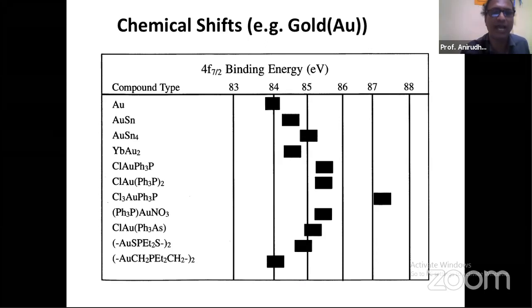This is a slide which shows different binding energies and binding energy shifts for an element like gold. The website Lasurface, which I mentioned a little while ago, would give information similar to what I have shown here, though not in the form of this graph. It would simply give those values. For example, gold shows a binding energy of 84 for 4f7/2. We will see what that 4f7/2 is. When gold is bonded with stannum, tin, Sn, the 4f electron binding energy for gold shows a shift, almost 84.5. When it is AuSn4, its value shifts to 85, and then you get a distribution. This kind of information is available in literature and on different websites.